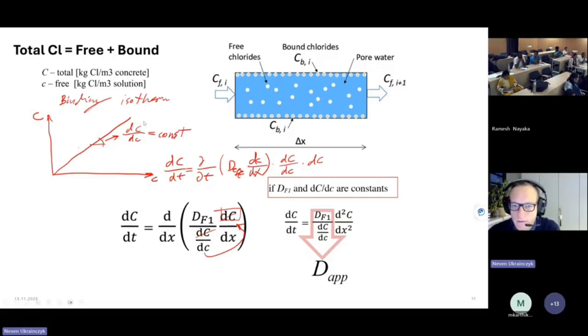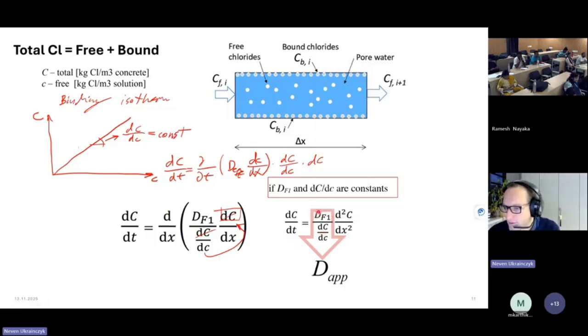The rate of change of total chlorides is a function of free chlorides. And then you have here the final. Maybe you are familiar with 1 plus the porosity, that depends on how you write the units. But in this way, if you write the units, then the apparent diffusion coefficient looks exactly like this. It's the effective diffusion coefficient divided by this binding slope. So now you can see it's the physical meaning for the diffusion, and also for the effective porosity, tortuosity, and the microstructure, just physical geometry. And this part is the reaction part. And this part actually can go here, then it's part of the accumulation, what I explained before.